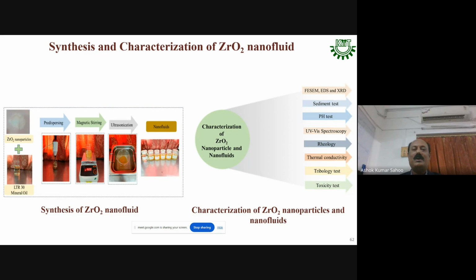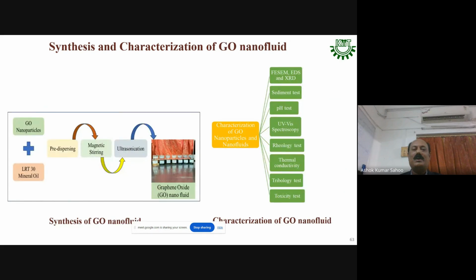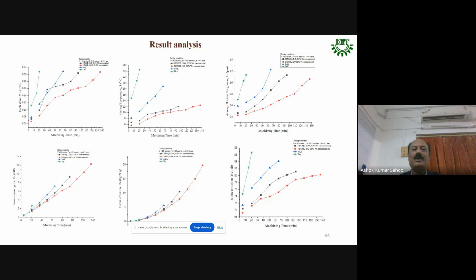Then nanofluids are prepared, and they have to be characterized. Many characterizations of nanoparticles have been conducted through sediment test, pH test, spectroscopy, rheology, thermal conductivity, and tribological test, and the toxicity property of the nanofluid has also been tested. Particularly, 2 important properties we have conducted here: thermal conductivity and viscosity, and toxicity, also whether it is toxic to the environment or not. Similarly, for graphene oxide nanoparticle, we have prepared the graphene oxide nanofluid, and a lot of characterization we have carried out.